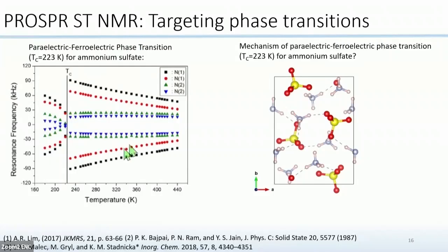Here we see a nice paper where they measured the N14 single crystal as a function of temperature. On the y-axis is the resonance frequency, and on the x-axis we see the temperature. We see that as a function of temperature, especially these 4 peaks of the single crystal, they change their position, and the CQ increases, and then below the phase transition, this is the critical temperature, there's an abrupt change.